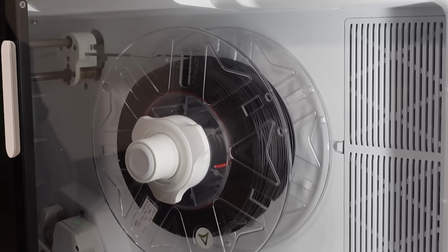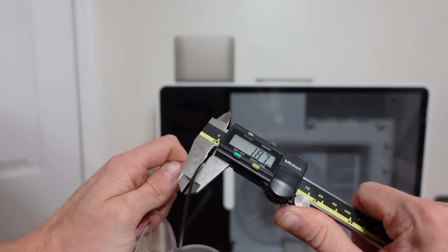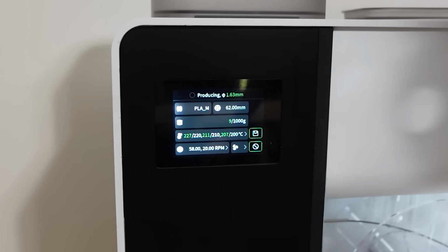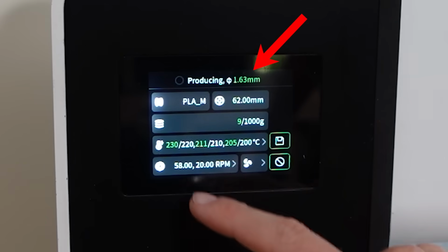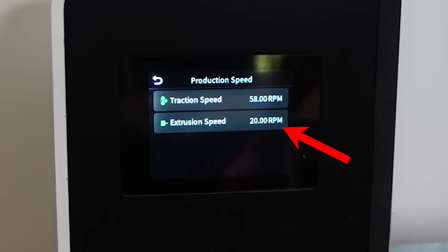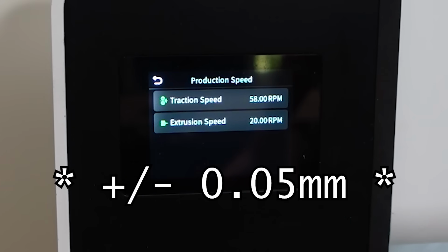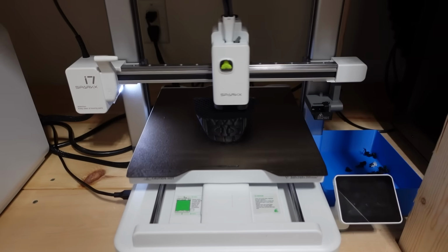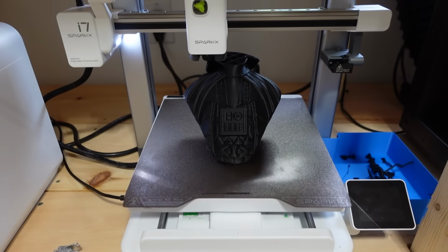After looking into it, I realized the filament diameter had gotten slightly oversized and led to a clog in the nozzle. This can definitely be avoided by monitoring the diameter readout and adjusting the traction and extrusion speed if the tolerance is starting to increase or decrease. To fix this, I measured the filament until it was 1.75 millimeters, cut it, and then restarted the print. The third attempt was perfect.